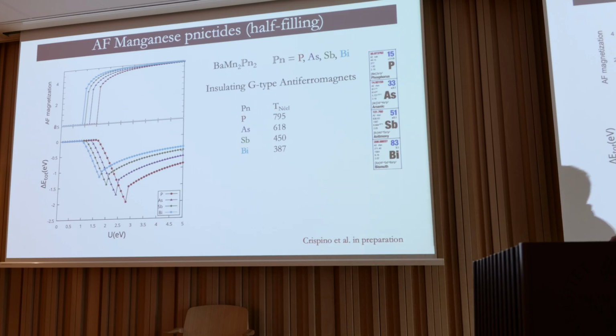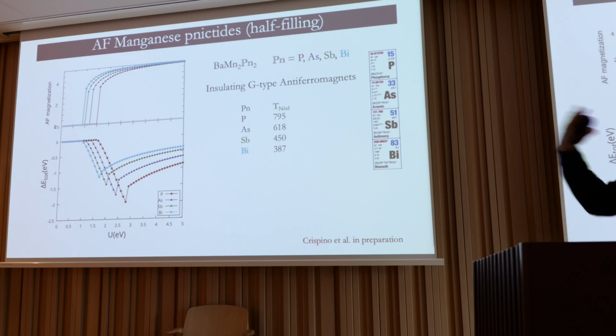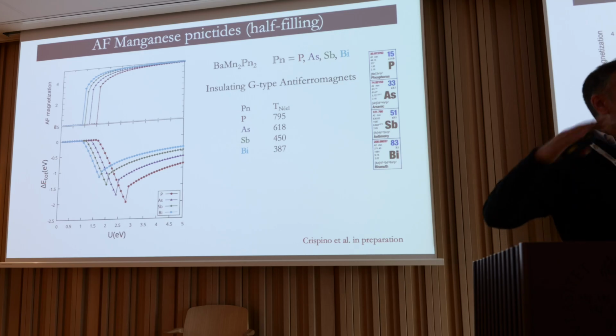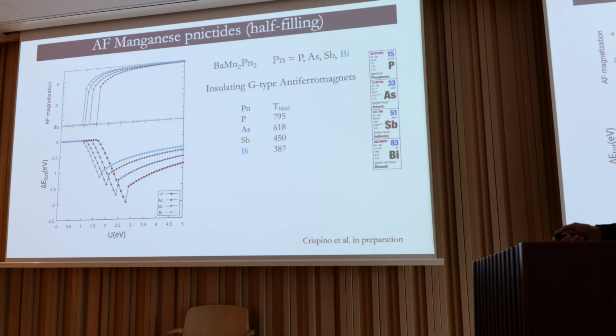And that's exactly what we find, because you can calculate the magnetization for all 4 compounds, which the colors are respected here. And then I plot here the difference between the energy of the paramagnetic phase and the energy of the antiferromagnet, which obviously is the ground state.